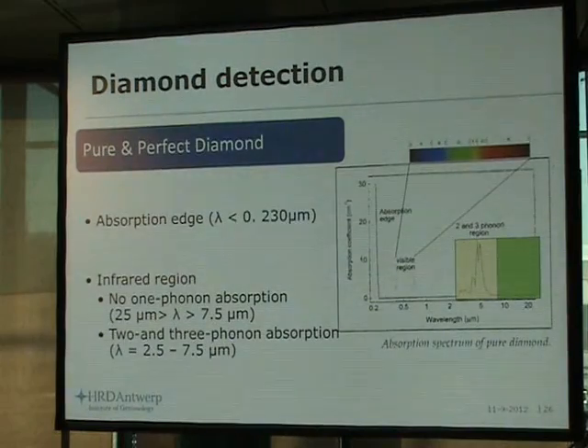If you look at a perfect and a pure diamond, then if one irradiates the infrared light, you get this kind of typical curve. So it's very clean, very, I would say, simple, and that is compared to the visible light region. So this is typical for a pure diamond.